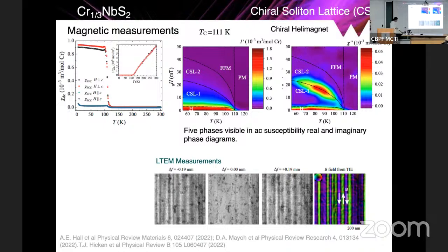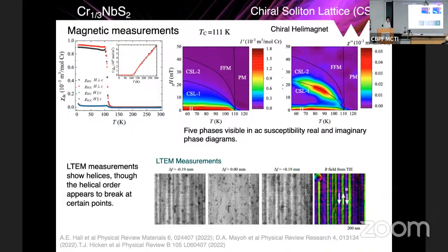Now, this is also supported by the Lorentz transmission electron microscopy that I told you about. And there, by doing measurements both in the under focus and over focus regime, you can actually see the formation of the helices in very, very thin lamellae of these materials.